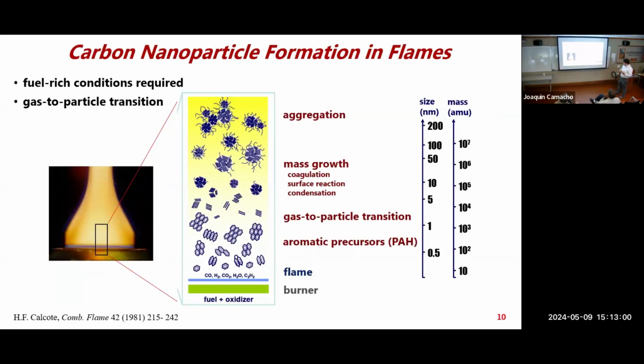The actual soot formation process is a specific gas to particle transition, whereby if you have fuel-rich conditions in the flame, it could be non-premixed or premixed, but as long as there's some pocket where there's a lot of hydrocarbons, if the temperature is high enough, it'll either break down or it will build itself up again. It'll build up into these aromatic precursors, and at some point, these aromatic precursors will transition from gas-phase species at high temperatures into a solid particle at high temperatures, starting from like 1 or 2 nanometers. This transition occurs at a very, very small scale, almost molecular scale.